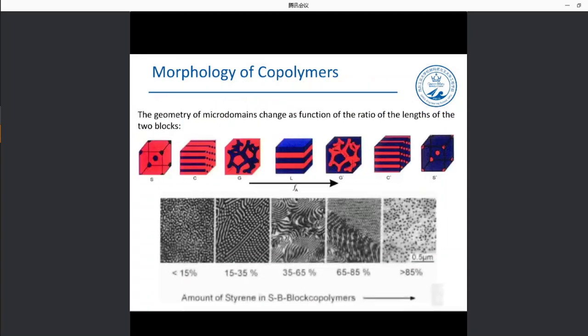nanoscopic patterns, okay? This is, let's say, the transition from a cubic to lamellar structure for a copolymer, with increasing fraction of the A monomer, okay? And as I told you, after 50%, when the volume of A is higher than 50%, we inverse the situation. So here we have an inversed